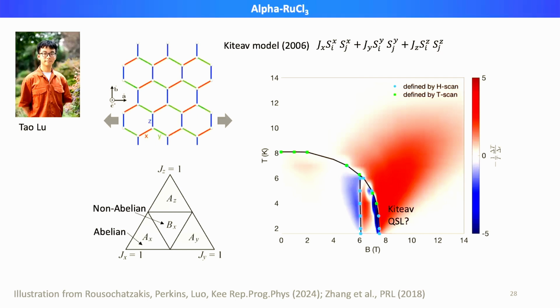Maybe a follow-up. Some parts are blue, some parts are red, and I guess those are opposite sign in response. That's correct. Let me get a little into the detail of the measurement itself. You can think about this measurement as measuring the strain derivative of entropy. Whenever you have a peak, when you are at a field-induced phase transition, the entropy of the system will be at a local maximum. If you take the derivative over some parameter, the maximum would give us 0, because we're taking the derivative of entropy. So you see a very characteristic dispersion curve if we take the field cut through this. It's consistent with the fact that the probe itself is sensitive to the entropy of the system.